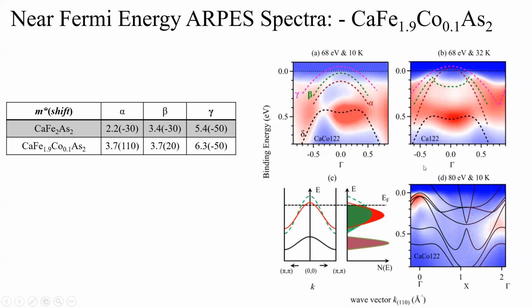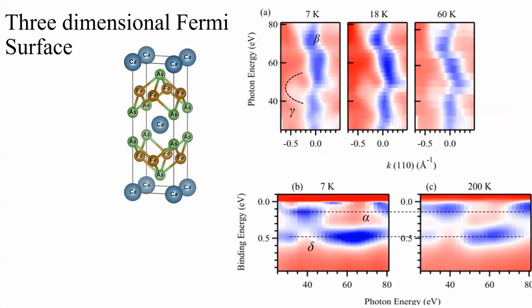Higher binding energy states means the higher binding states of the valence band or the core level. So even if I dope electrons at the iron side by replacing iron with cobalt, due to the band renormalization, I won't see any change in the binding energy position of these higher binding energy states. What else do we get with cobalt doping at the iron side?